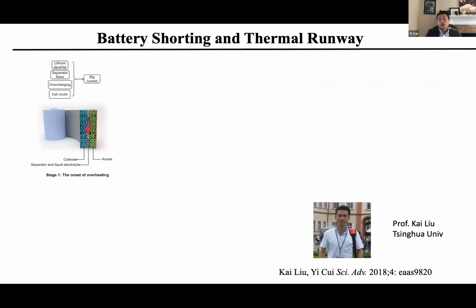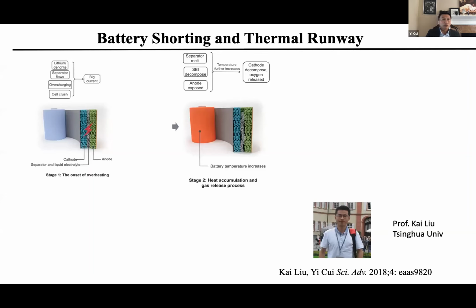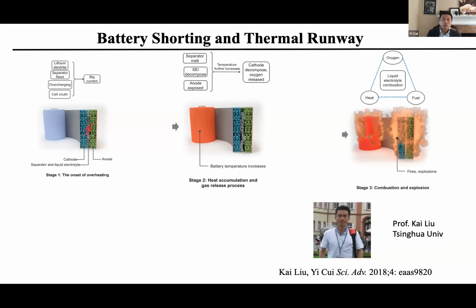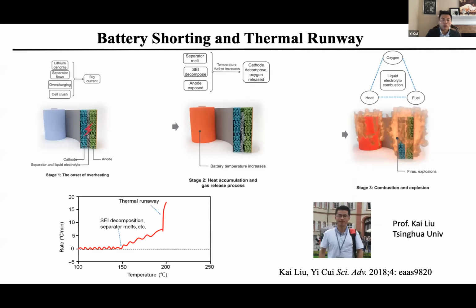So let me go one step further in terms of the materials and chemistry. If you have a shorting happening, and this shorting can be induced by many reasons, I believe later our speakers will tell you more exciting studies on this. And Chaoyang also mentioned, once your temperature goes up, because of all these phenomena happening, SEI decomposition, chemical reactions start to happen at roughly about 200 degrees Celsius. For the NMC cathode, you can go into the regime of catching fire. So we look at the rate of heat generation through this temperature at about 150 degrees Celsius also.